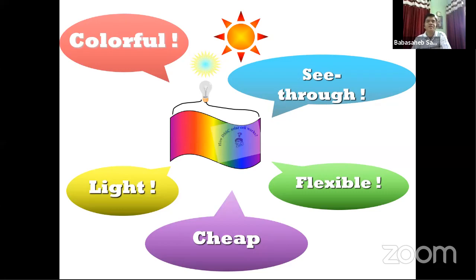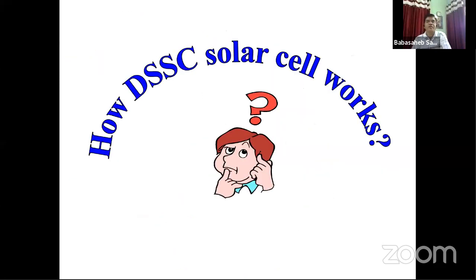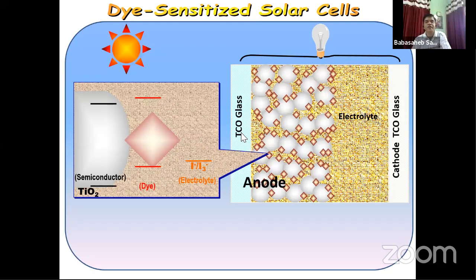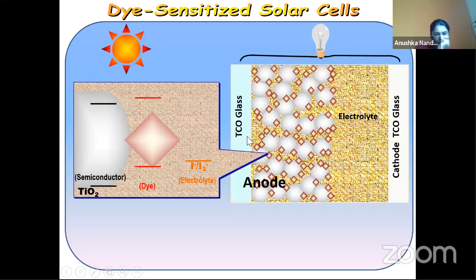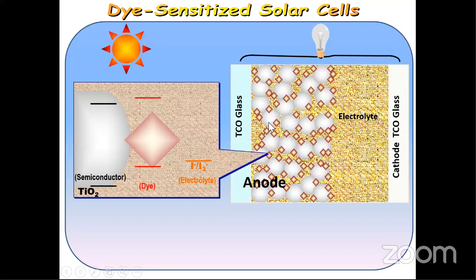So how does this dye-sensitized solar cell work? The construction is depicted here, as you can see in the block diagram. On the right-hand side, there is a TCO, called a transparent conducting oxide, which is coated on the glass substrate. Usually FTO is used to coat the glass substrate so that the glass is conducting as well as transparent, so that you have a transparent conducting layer on which you coat the nanomaterial.